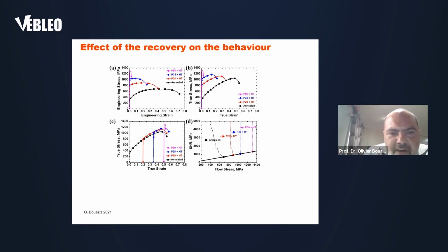So we can see now the effect of the recovery after pre-strain at liquid nitrogen temperature. So you see the as-received condition, and you see the curves after different pre-strains of 20, 35, and 50%. After the recovery, if you superimpose the curves shifted by the amount of pre-strain, you see clearly that for a given pre-strain, the strain hardening is improved after pre-strain and recovery treatment. So you can summarize in the Kocks-Mecking plot as I show you here, and we have improved the properties of high entropy alloy applying this metallurgical route.